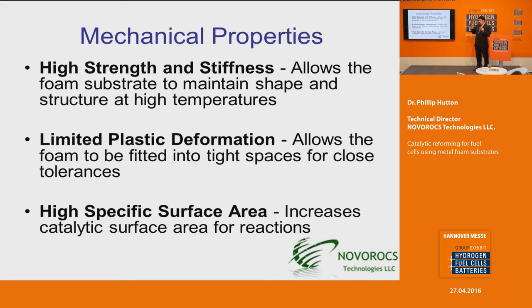There is limited plastic deformation. What this means is that we can take the foam, and if we want to maintain very close tolerances between the catalyst and the reactor vessel, we can oversize the foam just slightly and fit it into the reactor vessel so that there's no slippage of gases through the sides. And also, if we're worried about heat transfer, we want to maintain as tight contact as possible. And that's an advantage of metallic foams that you won't see in ceramics or ceramic beads.